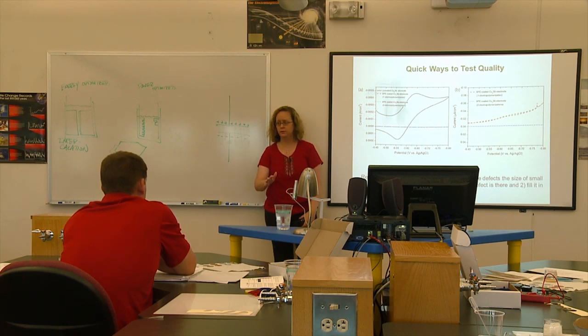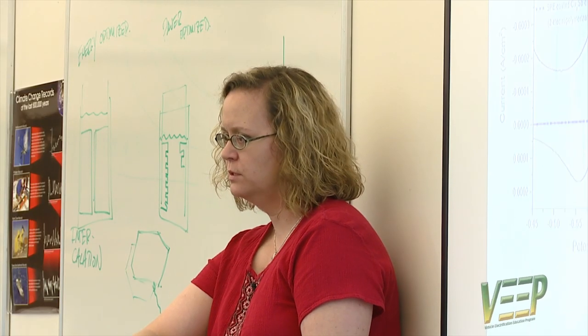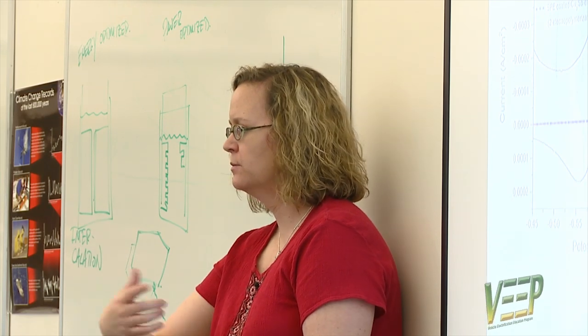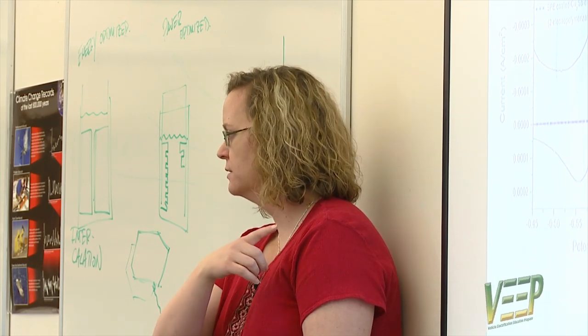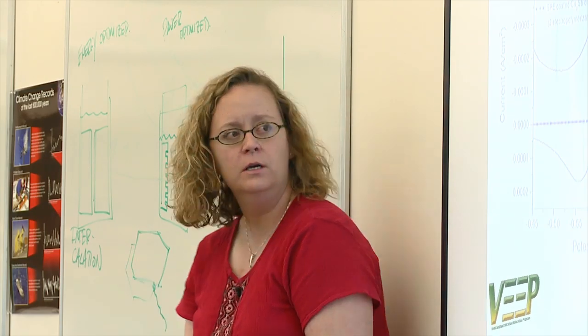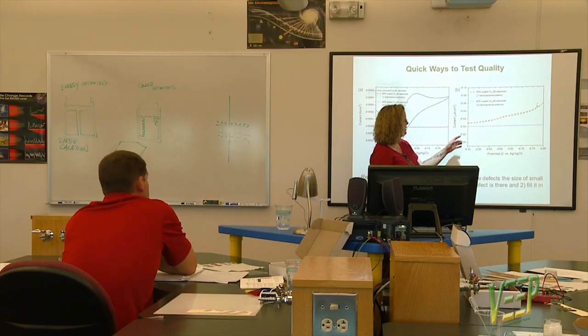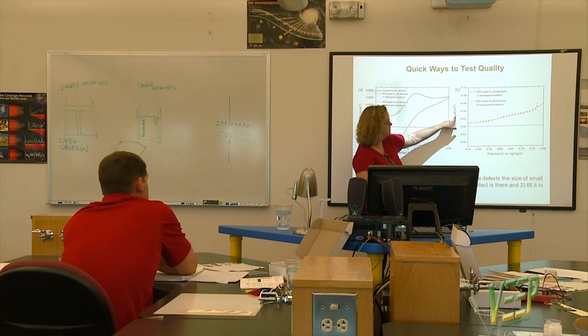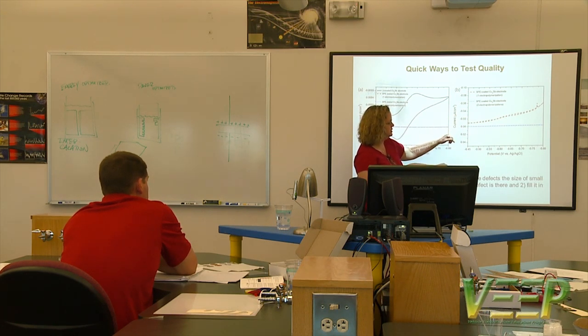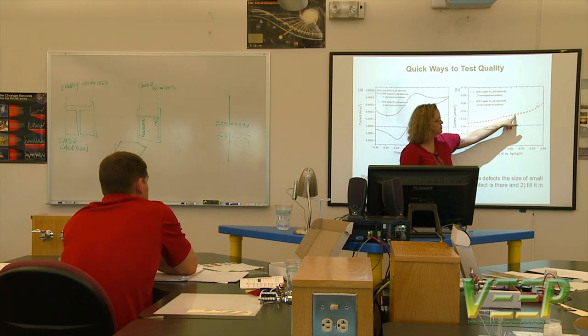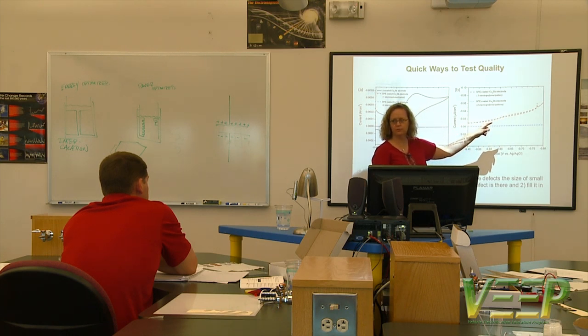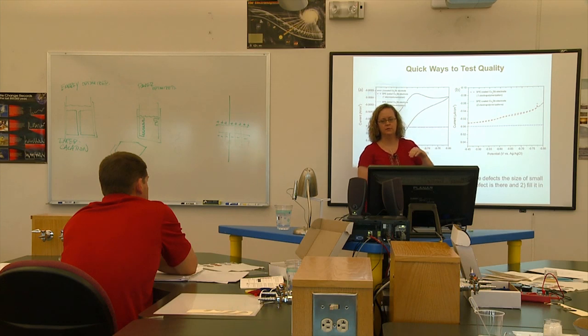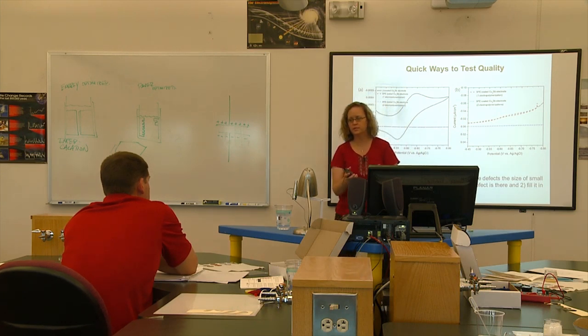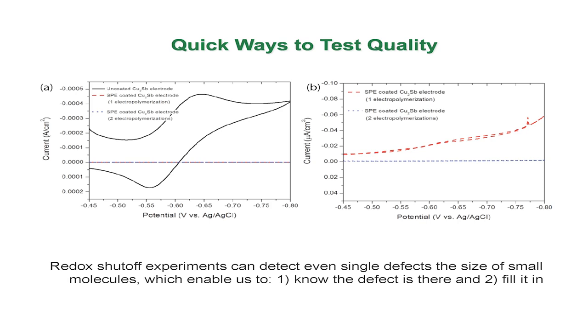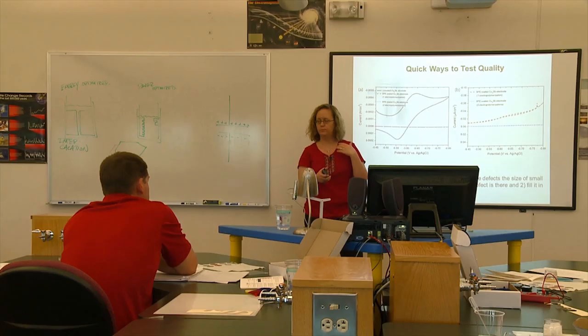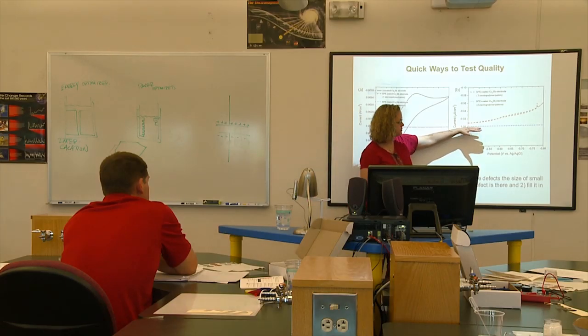If you see a pinhole anywhere, you just put it back in the solution with the monomer, you cycle one more time. The polymer will only grow where there's a mistake. Then you test it again and there's nothing there and you know that you're good. Now, this is what I mean by really sensitive. So now we're at microamps. After the first polymerization, you do see a tiny bit of this shape. It's not a real duck shape, so we know it's not a real pinhole defect, but what it means is that there is somewhere on this whole electrode that's thin enough that the polymer is diffusing through and could be a weak spot. So we polymerize again, one more cycle, and then it goes to zero.